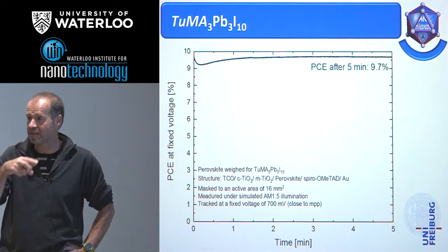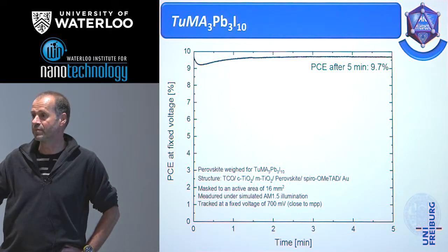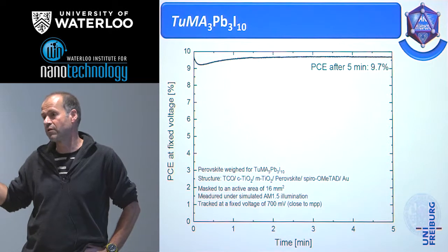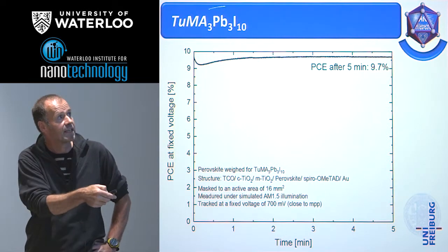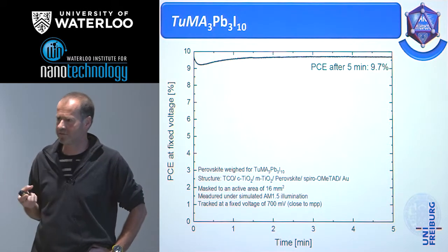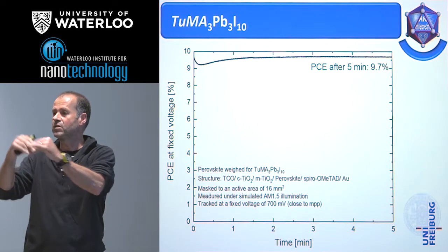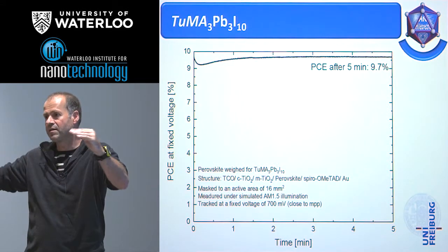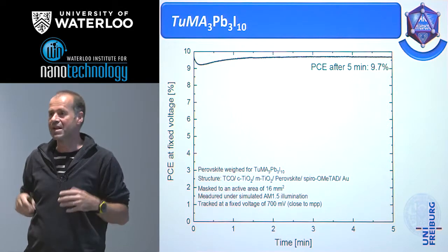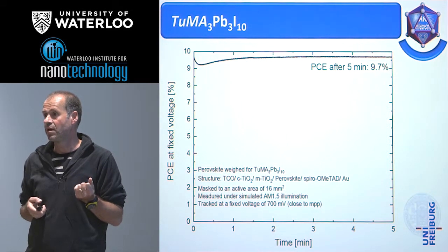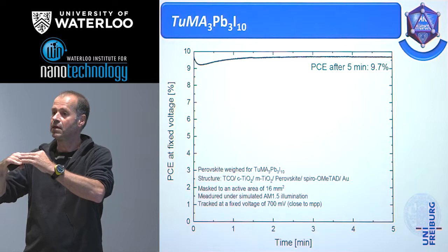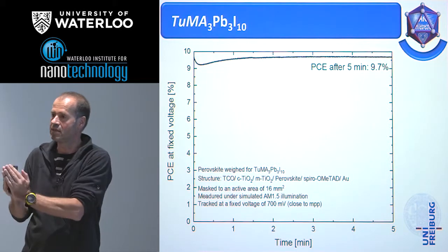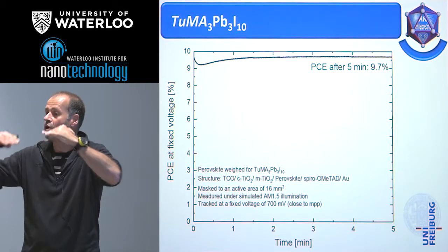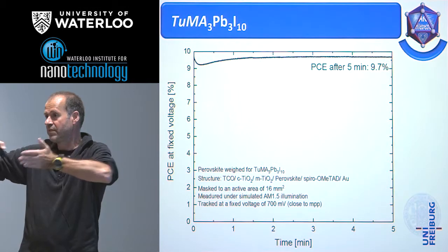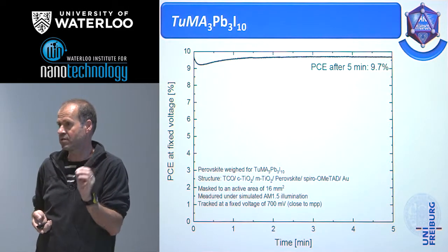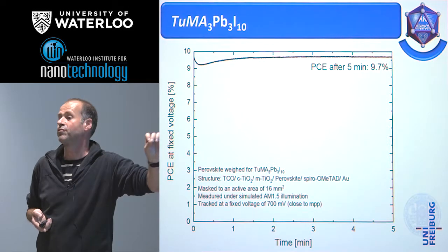And that's why I pointed out for our first example that it is really our red compound which produces this 3 or 4% efficiency. This is not clear in this case because the characterization of these layers is extremely difficult. Because if you do an X-ray investigation, you only investigate the small layer with, in my opinion, limited quality of the X-ray diffraction. And according to the common building principle, many reflections have the same position and the same intensity independent from the layer thickness, because it's always the same parameter. It's given by the structure. So the characterization is very difficult to say, yes, indeed, this compound is responsible for the properties.